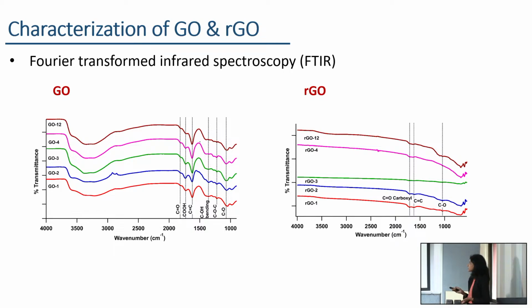After the reduction of this same graphene oxide into reduced graphene oxide, the FTIR spectra of these reduced graphene oxide show a significant reduction in the IR intensities corresponding to these oxygen functionalities, which is due to the removal of oxygen functionalities during the thermal reduction process.